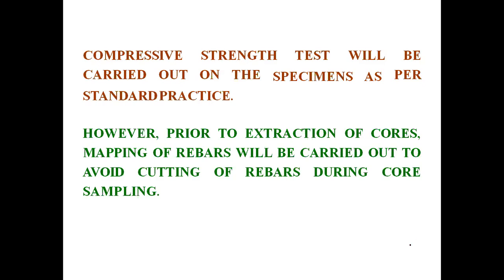However, prior to extraction of cores, mapping of rebars will be carried out to avoid cutting of rebars during core sampling. It is very, very important. When you are making use of this core test, you have to handle the cover meter test along with it, or use the engineering drawings of that particular structure, to know where the rebar is located.